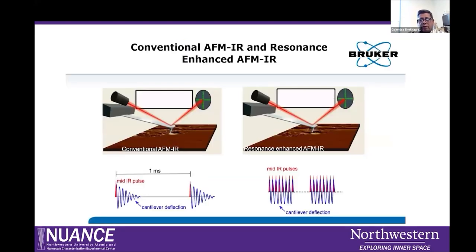There are a couple of different options we have on this system: conventional AFM-IR and resonance enhanced AFM-IR. Conventional AFM-IR is basically the contact mode. You bring the probe in contact with the surface, you shine your laser, there is thermal expansion, and you can read out those oscillations. With conventional contact mode AFM-IR, the resolution is a few nanometers. You can go to a depth of 100 nanometers, meaning if you have multilayer films, you can get a spectrum from different layers.